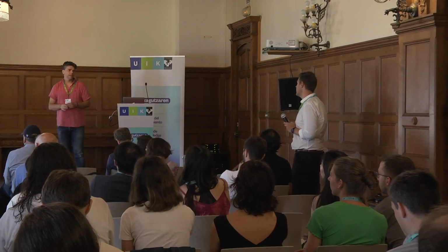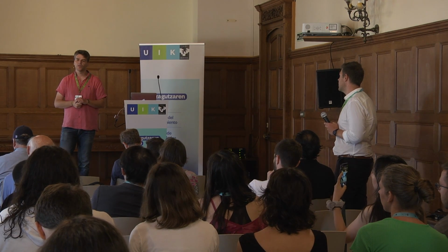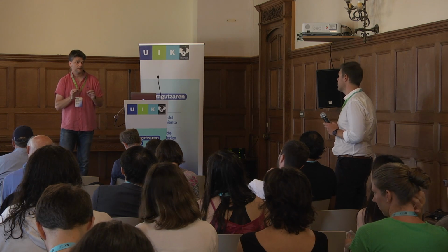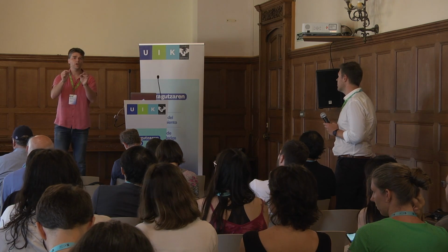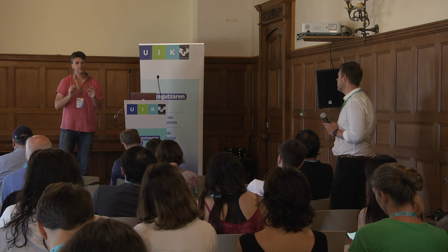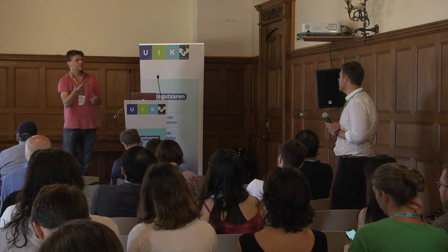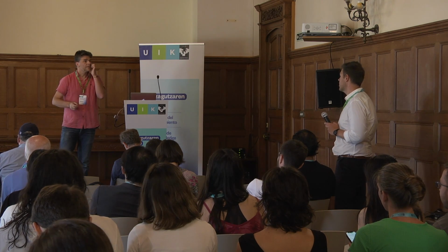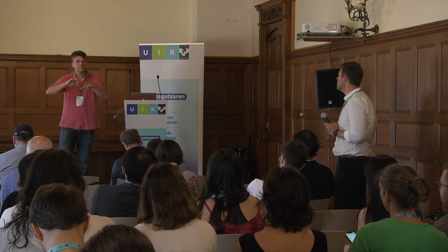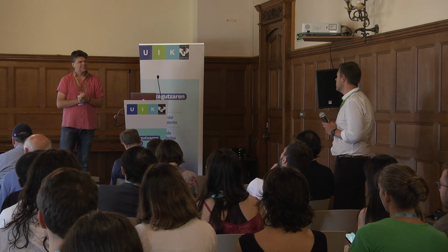These experiments, for the PhD student, were a three-year project. We started making the twisted structure, and we wanted a resonant antenna. We studied if we put it on the top, in the middle, or down. It could work more or less in every place, but we wanted to put it on the top. But by doing lithography and spinning the resist, the flakes were flying away. So we had to be careful to glue the layers and be gentle with them while making the lithography. This took a lot of time.